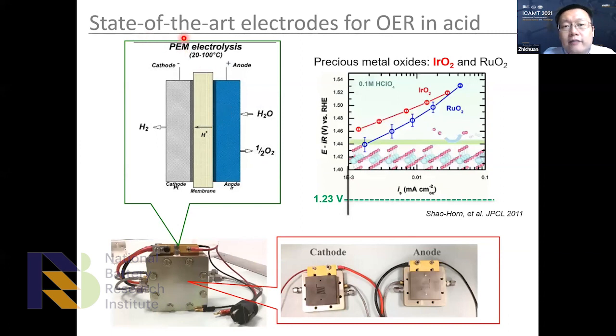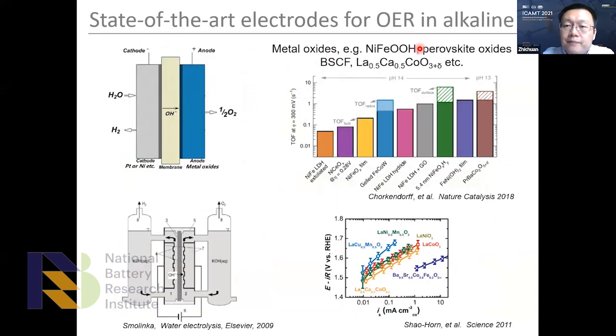If we look at the state-of-the-art electrodes for the OER, we have to look at the reaction media. In acid, we have to use noble metals because the acid is very corrosive and it causes corrosion on the electrode materials. So we have to rely on the noble metals. But if we look at alkaline medium, in that case we have to change the membrane to an anion exchange membrane. In this case, we have a lot of choice as electrode materials. We do not have to rely on the noble metals, and we can use transition metals and their based oxides, for example, nickel iron oxyhydroxide and perovskite oxides, etc.